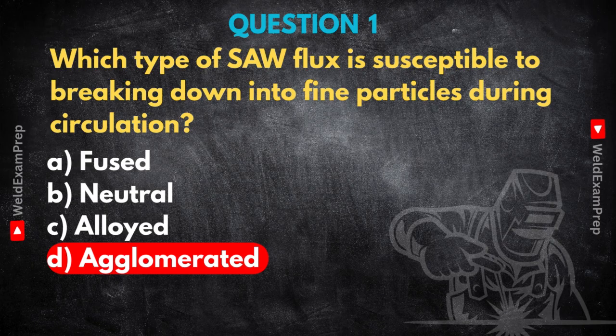So, for you listening, if you're an inspector and you know agglomerated flux is being used, what should you be looking out for specifically because of this breakdown issue? That's a really good practical point. What you really need to pay attention to is the condition of the flux itself as it's being used and reused. How do you do that? Well, the key check is the sieve analysis of the recirculated flux. You need to do this regularly. To measure the fines. Yes, exactly. It quantifies how much fine powder is building up. If you see a big increase in fines, that's your red flag the flux is breaking down.